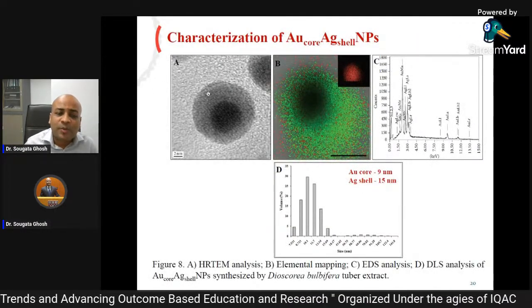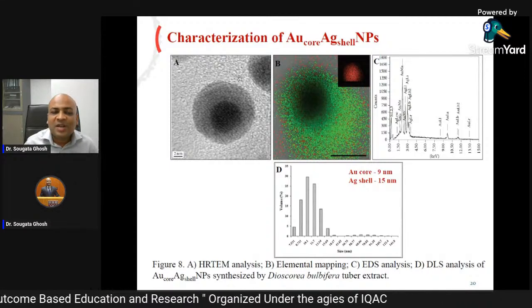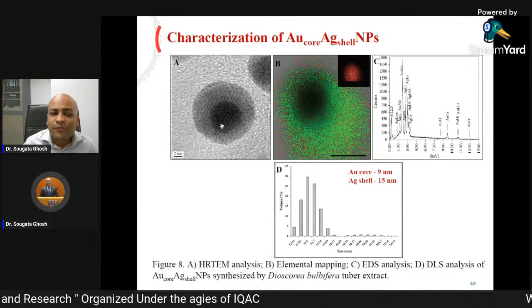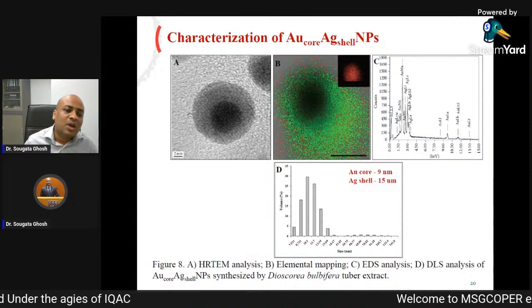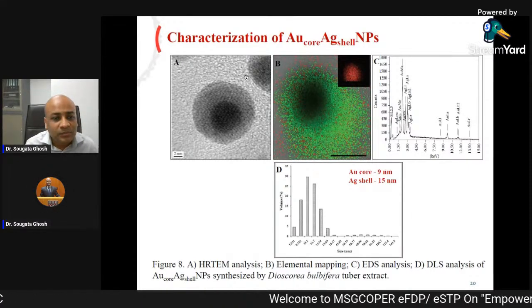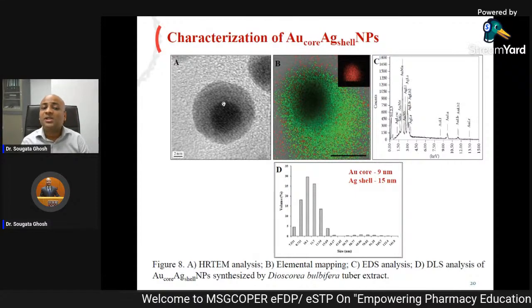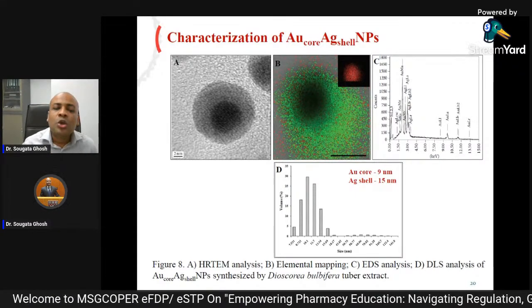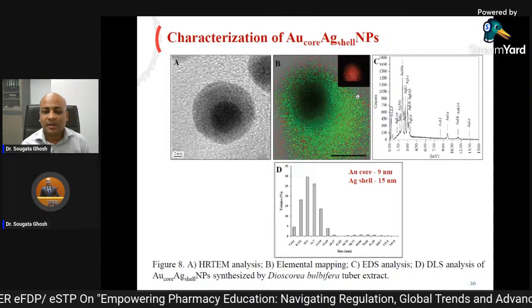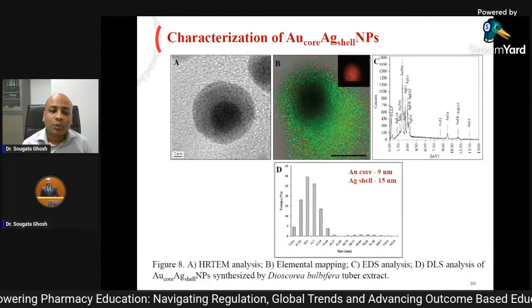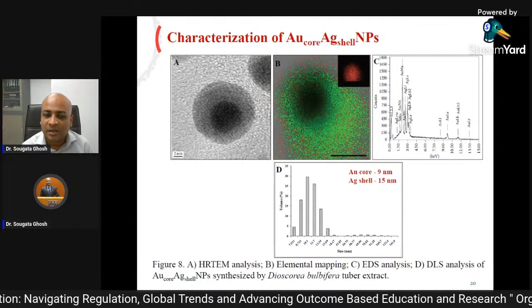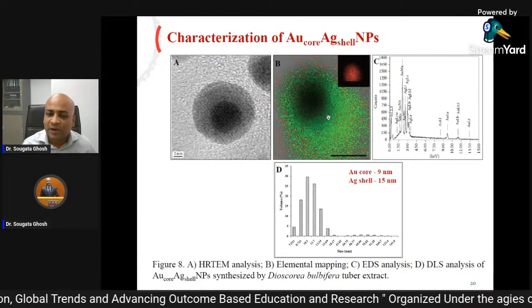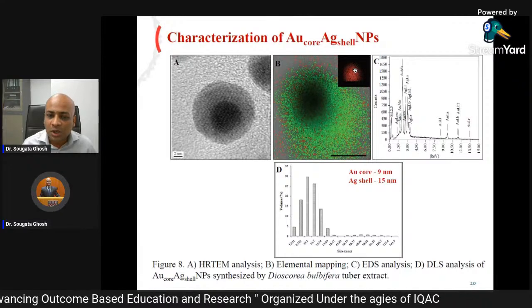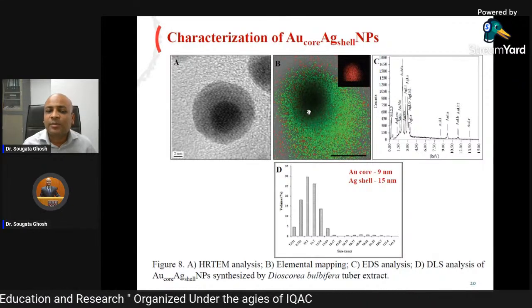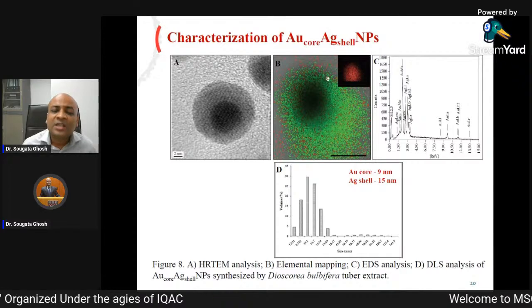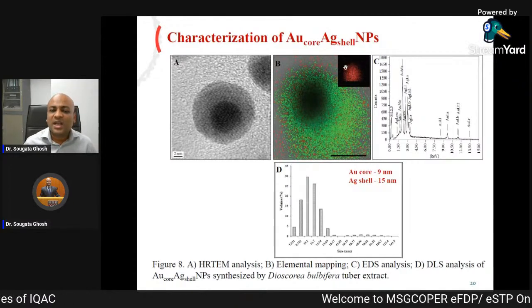We did another microscopy, that is HRTEM, high resolution transmission electron microscopy. And we found something was in the center and something was in the periphery, something was outside. But at this point, we did not know what was inside, what was outside. So there is a process called elemental mapping. In elemental mapping, we give a color code to different elements. So here we have given green color to silver and red color to gold. And we could see red was masked by green color. So that means silver was outside and gold was inside.